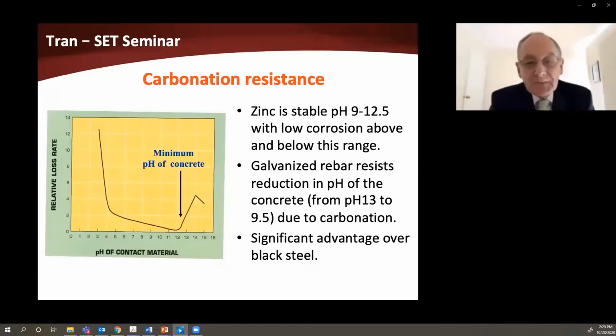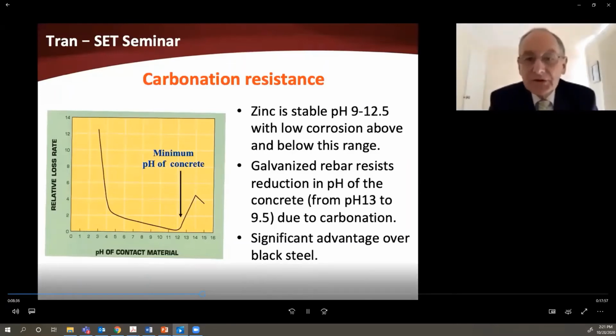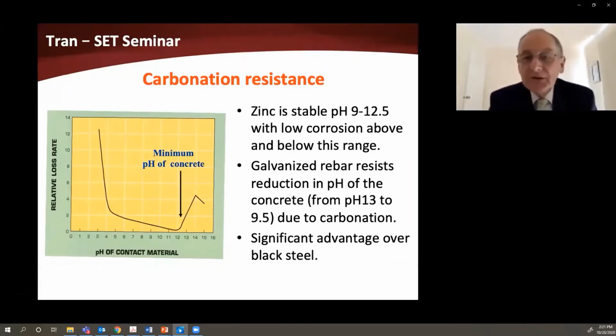The first thing is, what we know is that galvanizing has a resistance to both the effects of carbonation and also high chloride tolerance. Now, carbonation is a natural process that occurs in concrete due to the neutralization of the highly alkaline environment of concrete as acids from the atmosphere, carbon dioxide, and in polluted areas, sulfur dioxide, nitrogen dioxide, they dissolve in water as it rains, and these absorb into the concrete surface. Now, the minimum pH of concrete is typically around about 12.5 to 13.